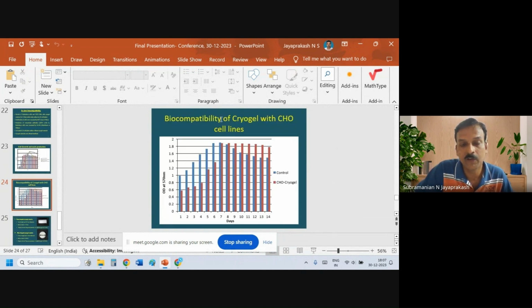And we also did the biocompatibility of this cryogel material with CHO cell lines. Here also we found it is highly biocompatible. Here you can see the blue color one is the control 24 well plate without cryogel, and the orange or red color is the 24 well plate with cryogel material. So it gave more or less similar cell viability. With this, we can conclude that these cryogel materials are highly biocompatible with the cell lines which we used for our study.